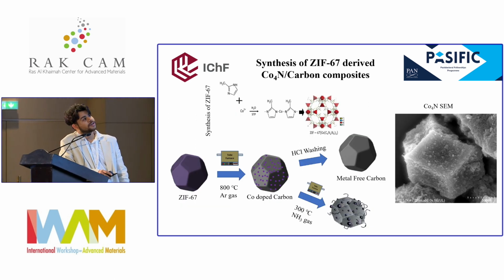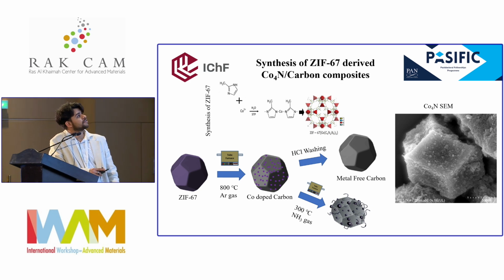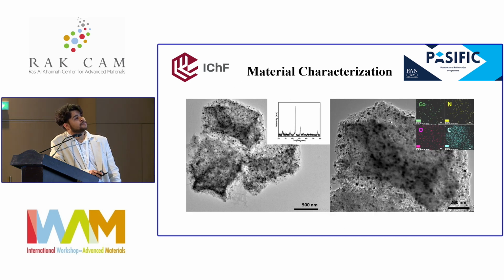In my work, I have used ZIF-67 MOF, which is a combination of cobalt metal and 2-methylimidazole framework. I have produced cobalt-doped carbon firstly through the pyrolysis method, and either we can produce metal-free carbon by HCl washing, or else we can react it with ammonia gas to produce cobalt nitride in the carbon structure. This is the TEM image of the material. We have produced nanosized cobalt nitride in the carbon framework, and the XRD shows the peaks of cobalt nitride.